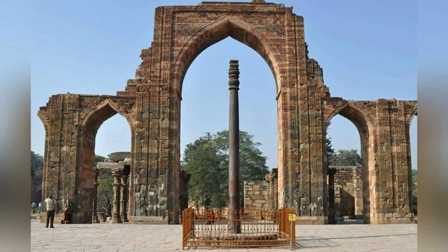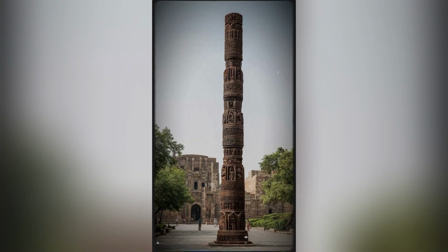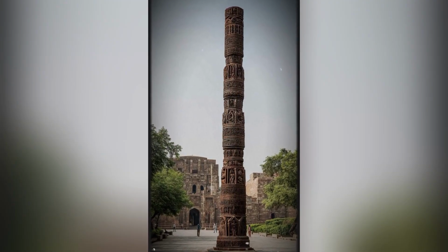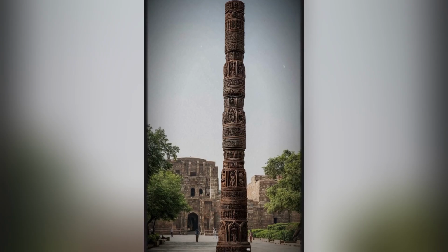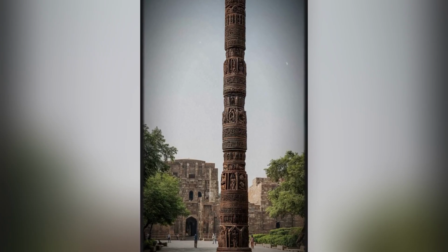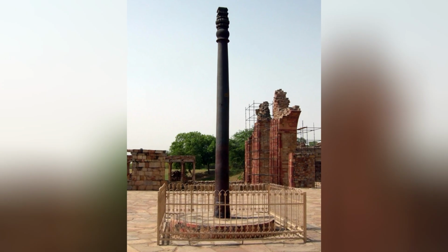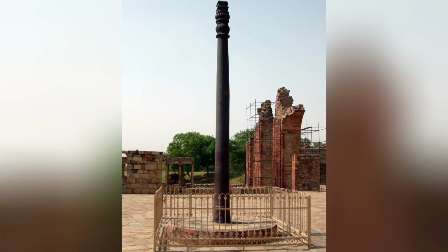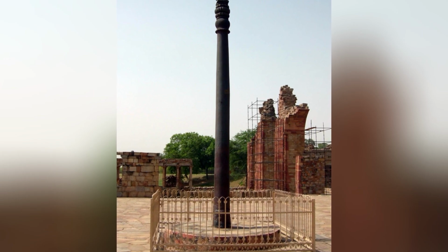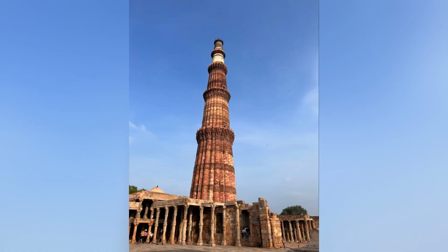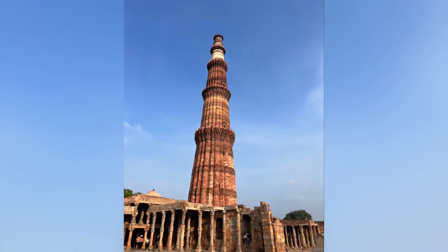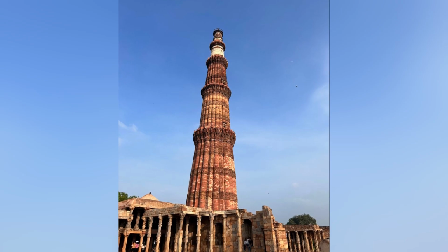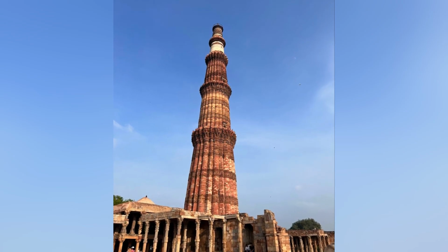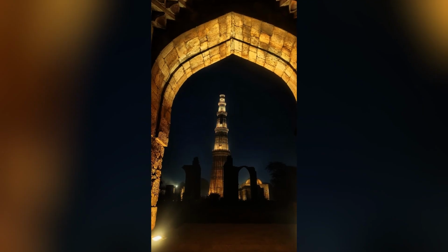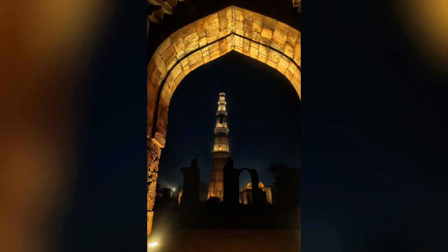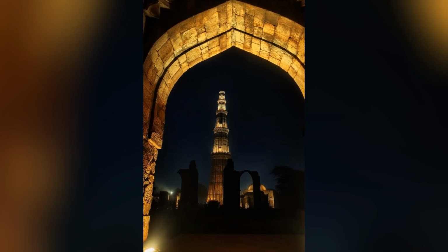The layered structure of the film, which is a consequence of the cyclic nature of the film formation process, contributes to the film's effectiveness as a corrosion barrier because the multiple layers provide redundant protection against the penetration of moisture and oxygen. The thickness of the protective film has been measured by cross-sectional examination of samples that have been removed from the pillar's surface. The film is approximately 50 micrometers thick, roughly half the thickness of a sheet of paper, and it is strikingly uniform, with a consistent thickness and a consistent composition across the entire surface of the pillar.